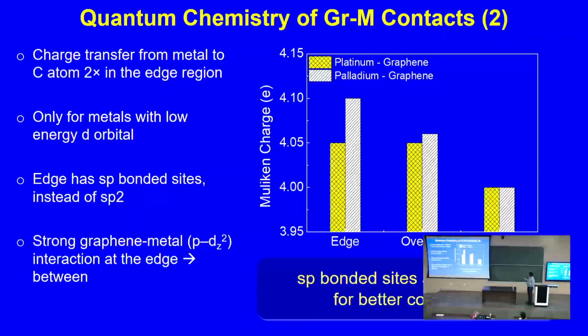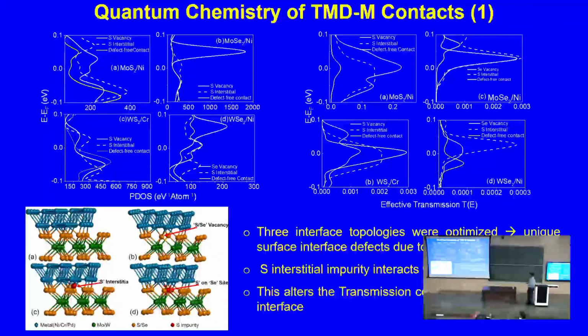Whereas in the case of platinum, the orbital energy is much higher, far away from the 2p orbital. There is no difference in the charge sharing, which means that even in the edge area, platinum is forming a Schottky contact. So for this bonding to happen, you need a metal which has a valence orbital with energy very close to the energy level of the 2p orbital of carbon in graphene. Now this is about the quantum chemistry of the graphene.